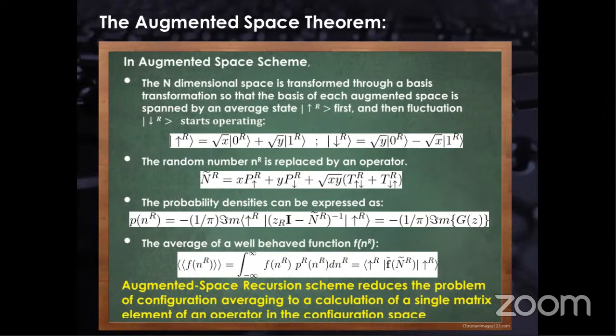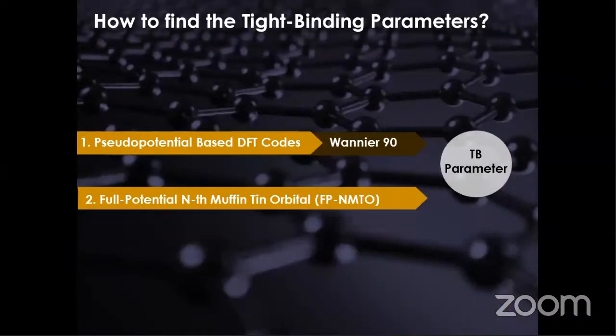But when we transfer this into augmented space, every site at first is occupied by an average state, then fluctuations come, and there are many mathematical steps which I should skip here. The main thing is that the augmented space recursion scheme can reduce the problem of configuration averaging to calculation for a single element of a matrix. That is the main trick, and it is becoming so fast for that reason. But we need tight binding parameters. Tight binding parameters can be extracted from DFT codes using Wannier90, or from the site-centered full potential N-th order Muffin-Tin orbitals also.